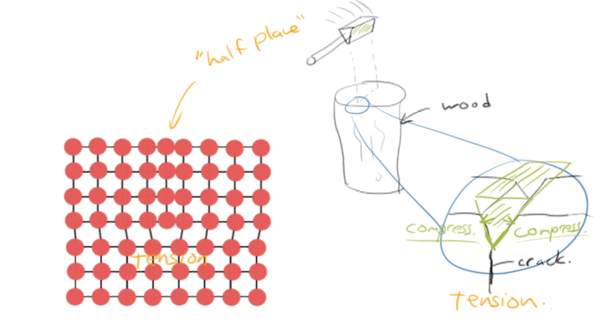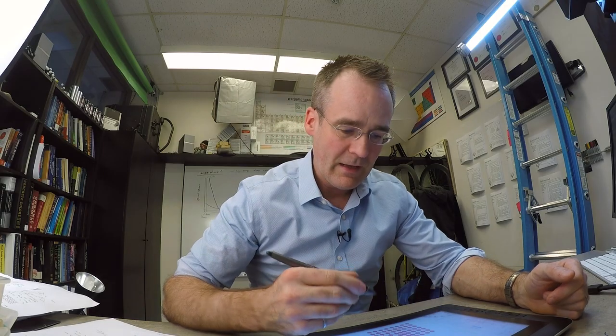They're being pulled apart. And I think what you can see up above the dislocation is that these are all in compression. So there's compressive stresses above the dislocation or above the tip of the dislocation. Sometimes we call this the dislocation line.